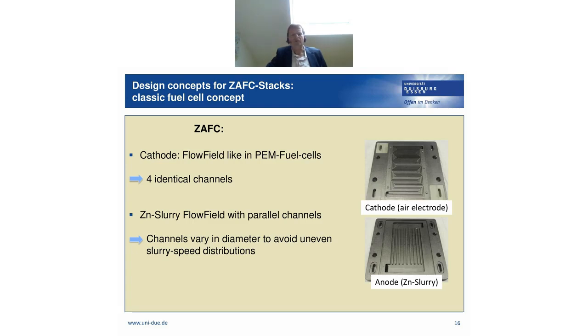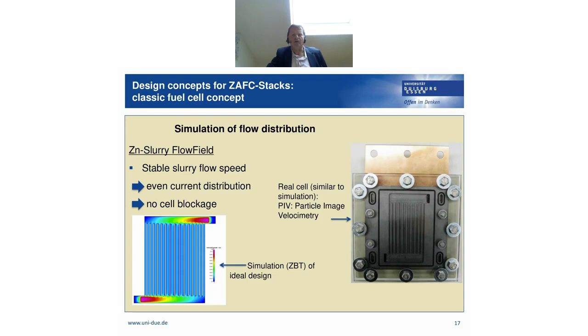And in the bottom, you see a zinc slurry flow field with parallel channels. The channels vary a little bit in diameter, which might not be easy to see for you, to avoid uneven slurry speed distributions. And we tested and also simulated the flow distribution in the zinc side of the cell. On the bottom left, you see a simulation of the flow speed. This might be much too small to read the speeds here, but you see it's quite a stable slurry flow speed that results in even current distribution, and we did not detect any cell blockage.